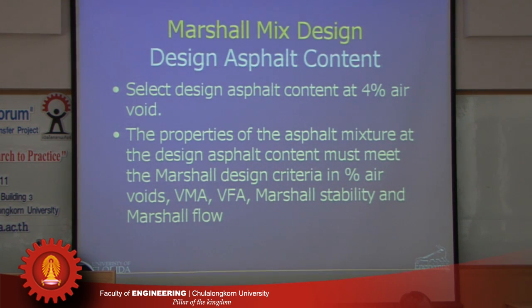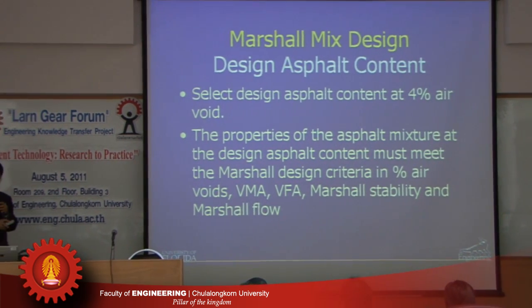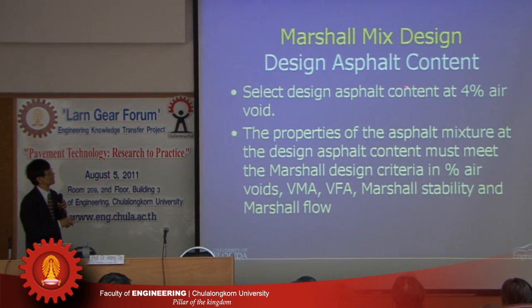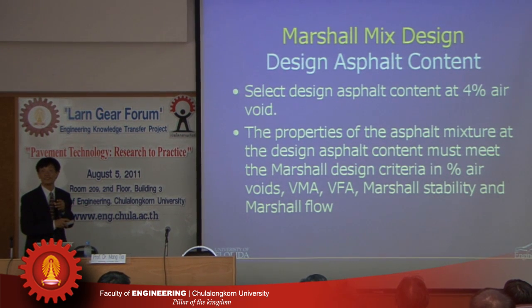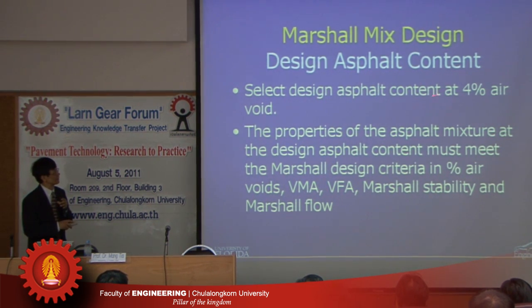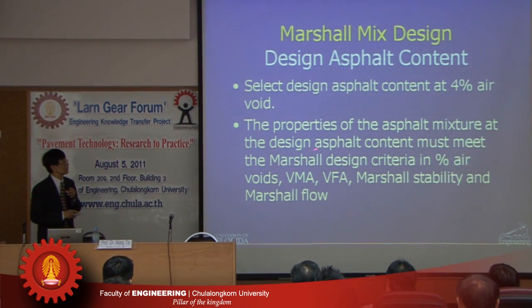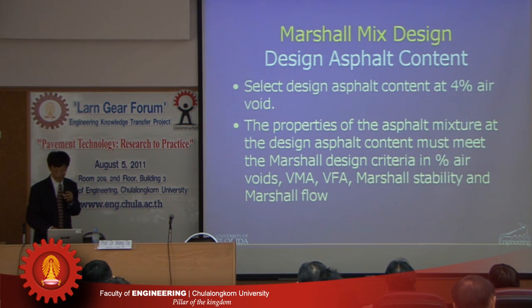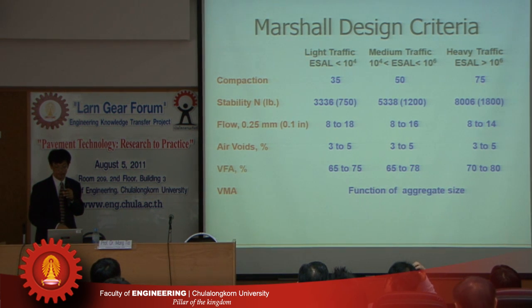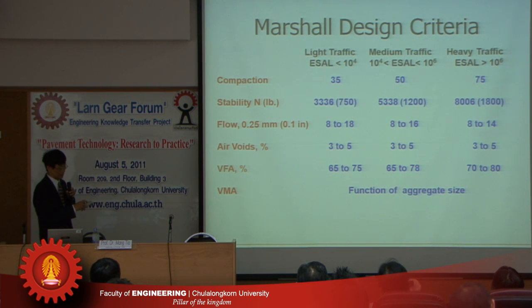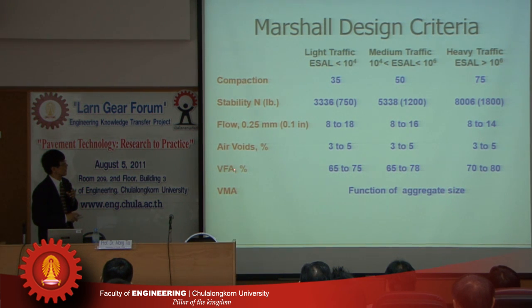Okay, and what is considered the optimum? The optimum asphalt content is picked when the air content is 4%. Okay. At 4%, that's where the optimum asphalt content is, and at that asphalt content, we look at all the other properties, and they need to meet all the criteria as shown here. Okay. So basically, the criteria includes Marshall stability, the flow, and then also these three properties: air voids, voids filled with asphalt, and VMA, that's voids in mineral aggregate. Okay, and now that, so